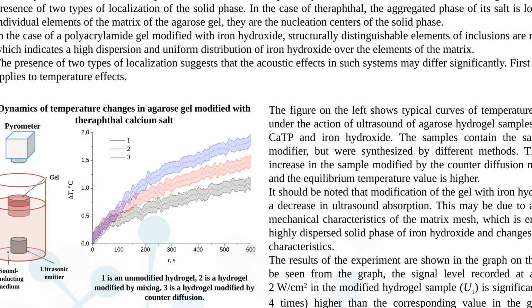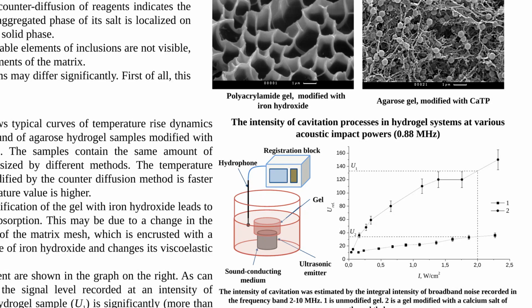It should also be noted that modification of the gel with iron hydroxide decreased ultrasound absorption. This may be related to changes in the mechanical properties of the polymer network. The highly dispersed solid phase becomes incorporated into the network and changes its viscoelastic characteristics.